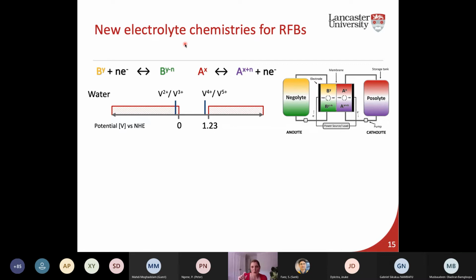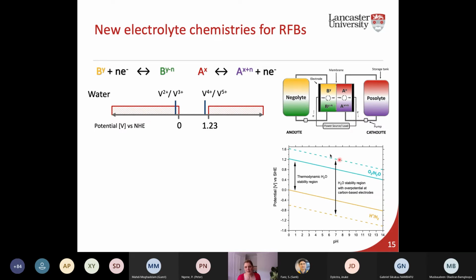We also need to consider not just what our redox species are doing, but also in what solvent they're operating. So if we're working in a water solution, an aqueous solution, we're looking at the vanadium battery. This is the thermodynamic window that you have for water, but of course your kinetic window is a lot higher. So you've got a thermodynamic stability region, and then a slightly higher kinetic stability window to operate within. So about 2 volts really.